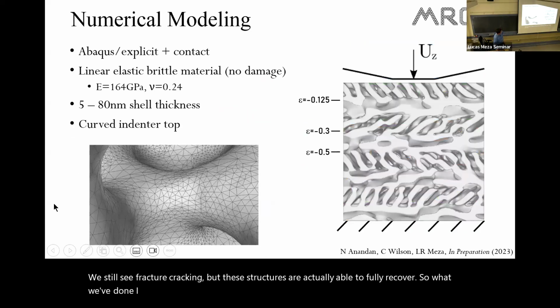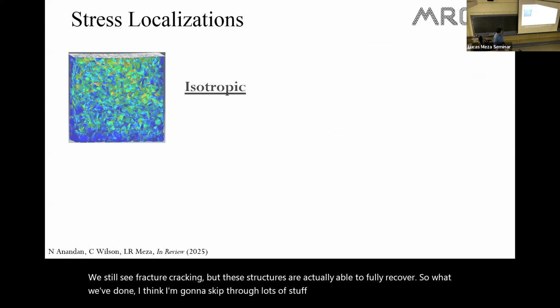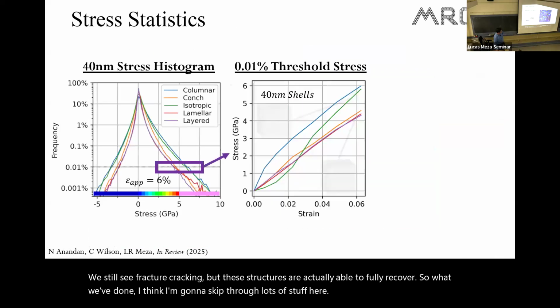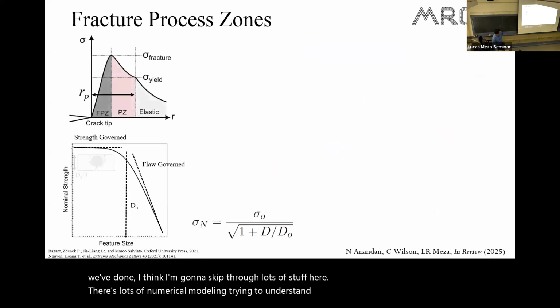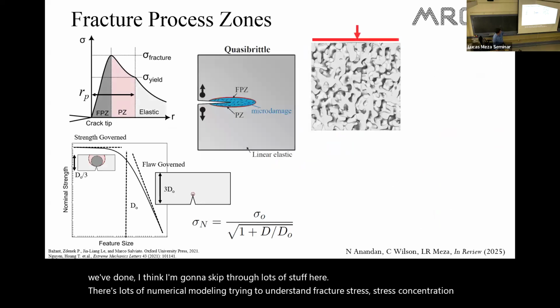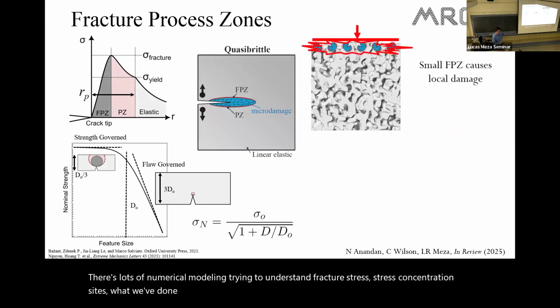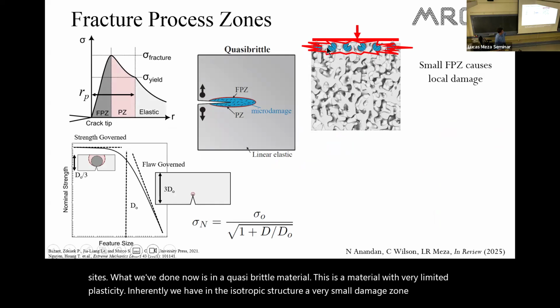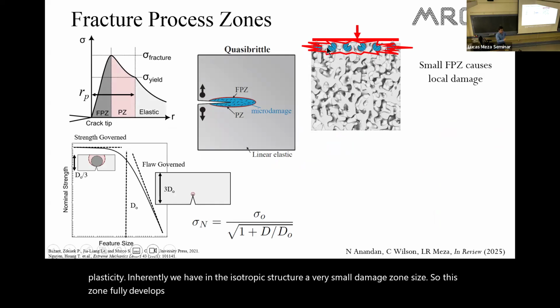So I'm going to skip through lots of stuff here. We did lots of numerical modeling, trying to understand fracture and stress concentration sites. What we've done now is in a quasi-brittle material, a material with very limited plasticity inherently, we have in the isotropic structure a very small damage zone size. So this zone fully develops, you get a crack, it cracks, the material is broken.